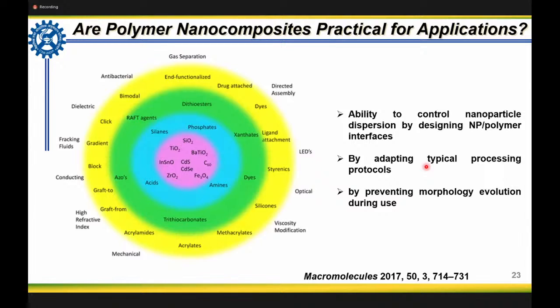There is another challenge. If you take polymer nanocomposites, to the best of my knowledge, for the last 3 decades several polymer groups have been working in this area. People use different kinds of nanofillers, for example 0-dimensional, 1-dimensional, and 2-dimensional. But unfortunately, when it comes to practical applications, it's difficult to get reproducible results because of many challenges. The interface between the nanoparticle and the polymer should be good, only then can we have reproducible results. So whatever inorganic nanoparticles or materials we choose, we have to modify them effectively before using them with the polymers.